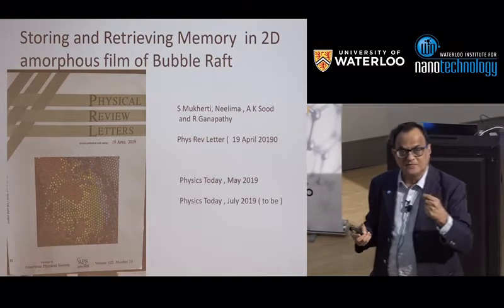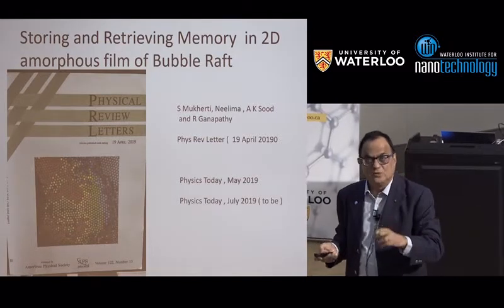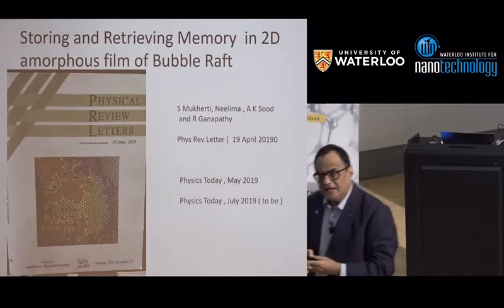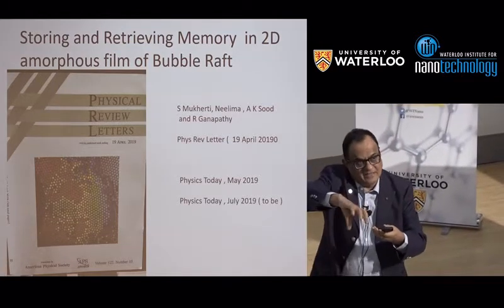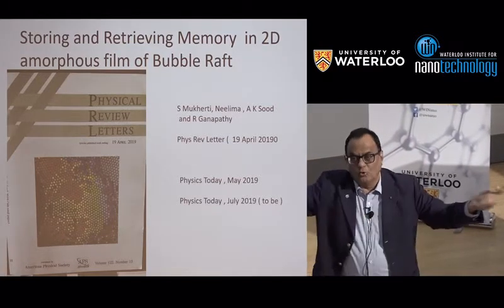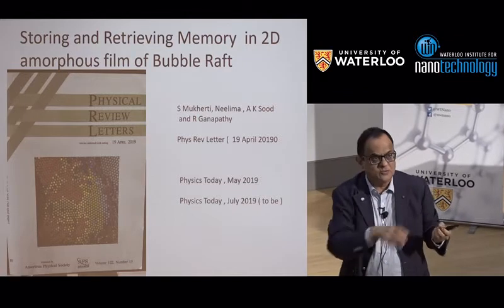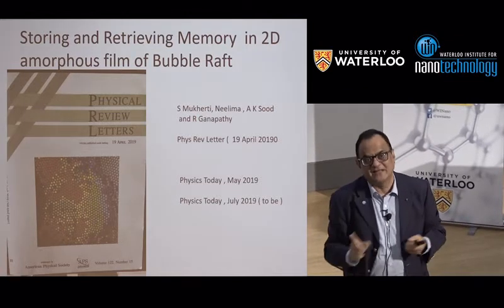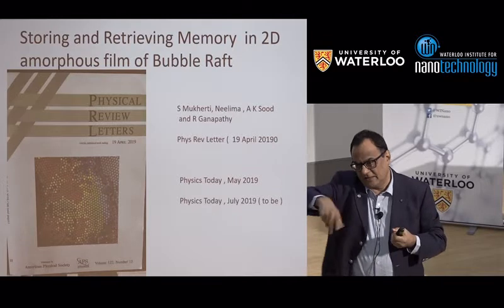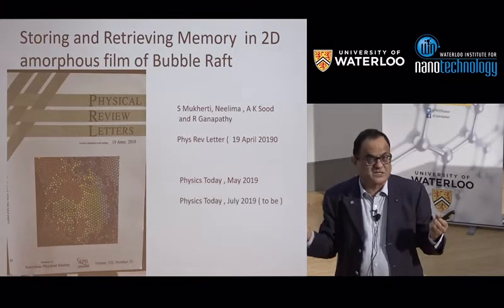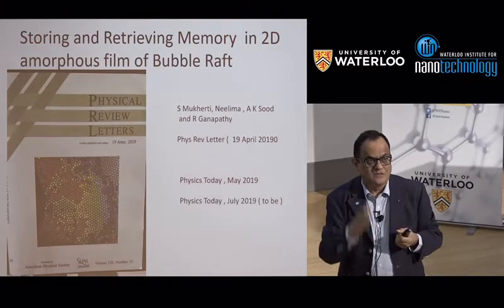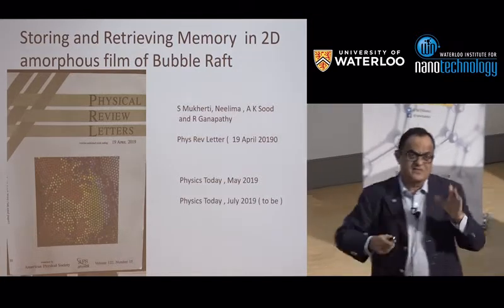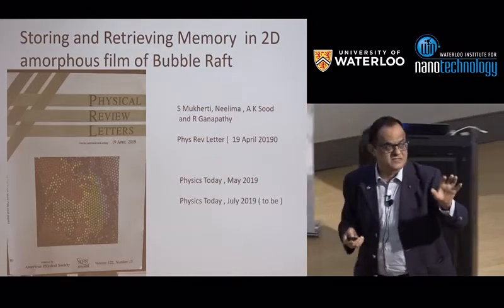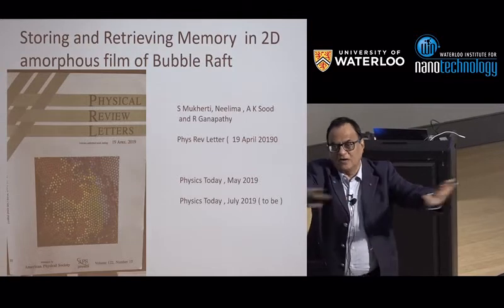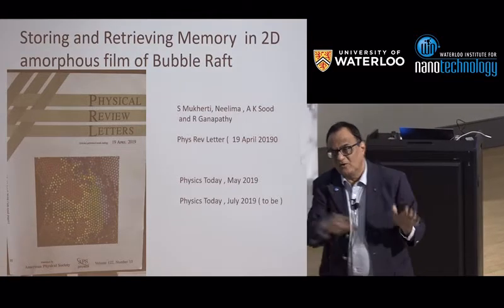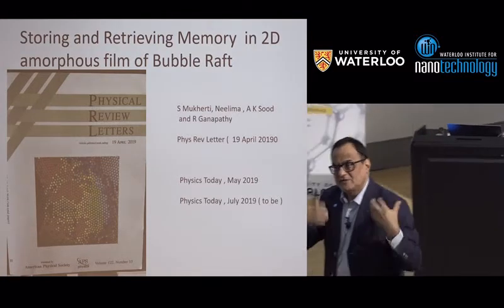What we have shown is, in that colloidal glass, you can store memory. So the idea is, you disturb it with some amplitude, then you go home, come back, and then you see that exactly at that shear amplitude, something happens in the measurement, and you exactly know the system remembers it. So this is the remembrance of the mechanical structure, which looks exactly identical. You can't make out there is a difference, but because it is a complex landscape, it stores memory.